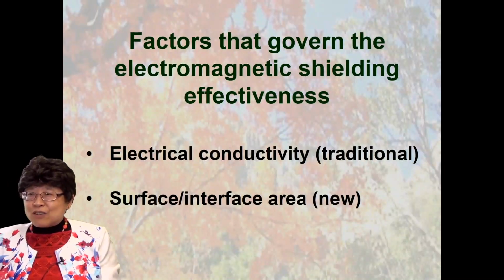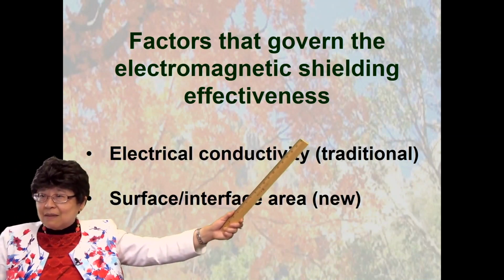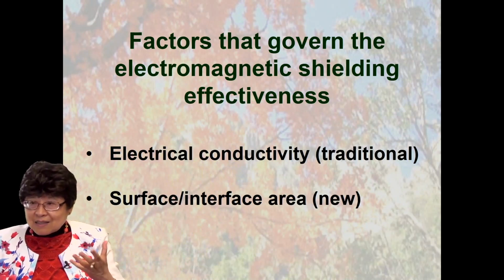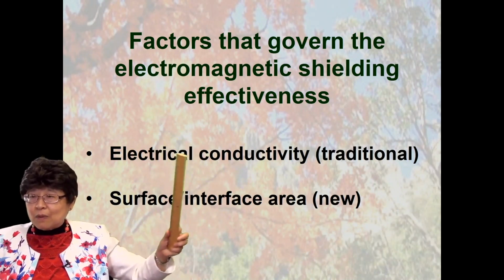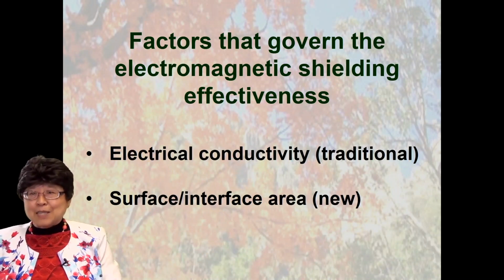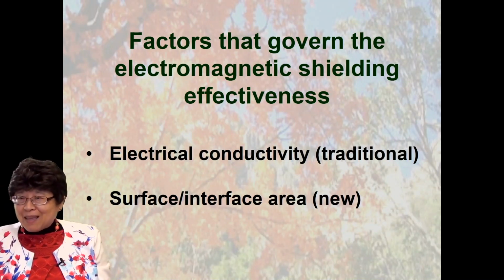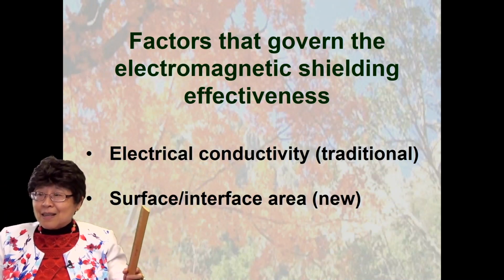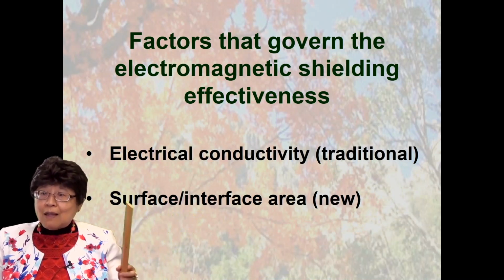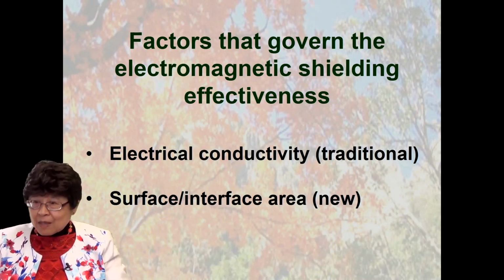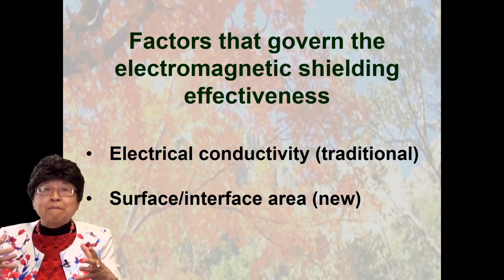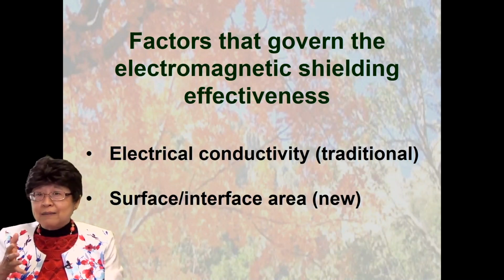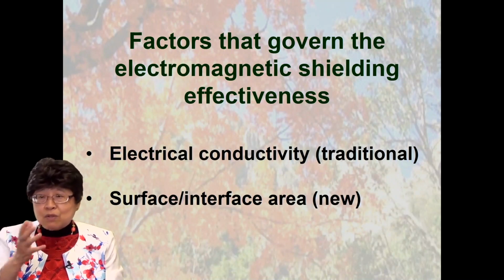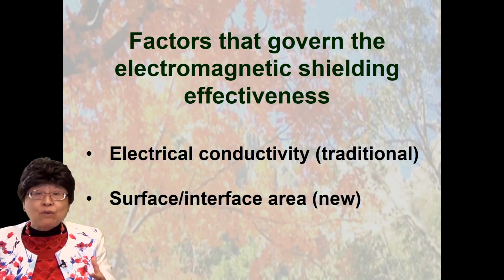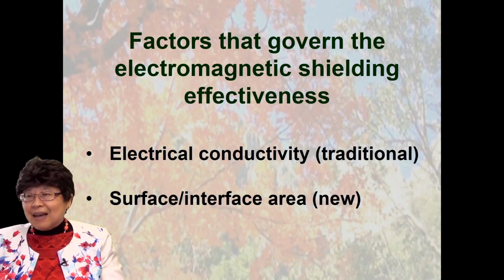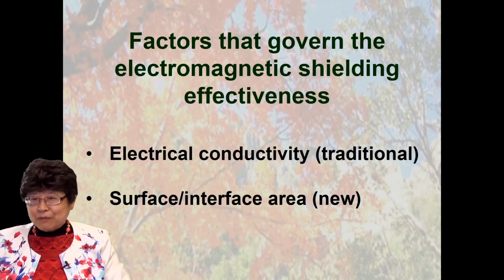The factor that governs the shielding effectiveness, traditionally, is the electrical conductivity. The higher the conductivity, the better the shielding. So that's been used for a long, long time as the specification for how good a shielding material is. However, what I realized is there's another important factor that people have overlooked, and that is the surface or interface area. The surface of the material, how much surface area, or if you have a composite, the interface between the different components of the composite. So whether surface or interface, that amount of area per unit volume needs to be high. The higher, the better. And that's the new criterion that I put forth.